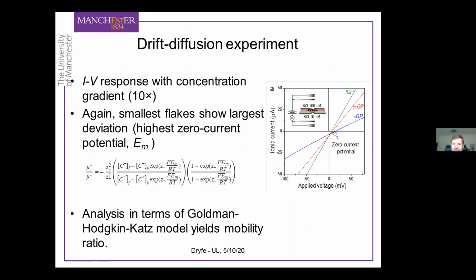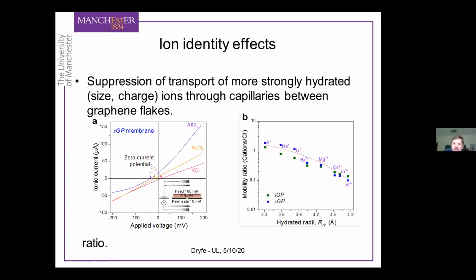And if we have an asymmetric concentration of electrolytes on either side of that membrane, we can look at the current voltage response for these different graphene membranes formed from different sizes of graphene platelets and do a kind of standard Goldman-Hodgkin-Katz analysis to extract the apparent mobilities, or the mobility ratio, of the ions moving across that membrane, because you always get this offset in the zero current potential, so you can relate that to the mobility ratio of the ions that are present in the salt. So you can get quite a lot of information from doing some quite simple experiments in this kind of drift diffusion configuration. And basically, to cut a long story short, you can measure the mobility ratio of ions in the membrane and look at how the transport of different ions through these graphene channels is suppressed relative to the transfer of chloride ions. So all ions are transported more slowly through the membranes, but basically, as you might expect, ions of higher charge are attenuated more as they travel through the membrane. So that's the type of analysis we've been doing, to get information on transport of ions through graphene membranes.